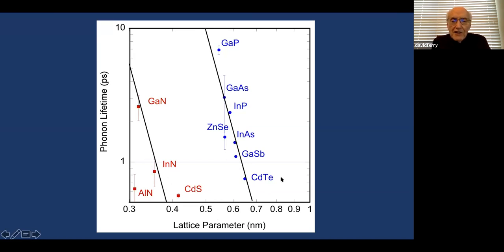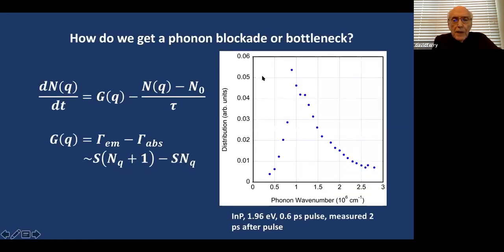And this is the one with gallium nitride. Now the zinc blendes look pretty good. The wurtzites, though, they're all over the place. Gallium nitride and indium nitride are doing what they're supposed to do. Aluminum nitride and cadmium sulfide, anybody's guess. I tend not to like aluminum compounds anyway, because if you leave the aluminum surface bare, it oxidizes, and so you get all kinds of crud on the surface. So that's a problem with that. But there's a scaling parameter in this for the lifetimes of the phonons. And so you can generally check and see if it fits with what you expect it to be in your measurements. Okay. Now, back to this curve.